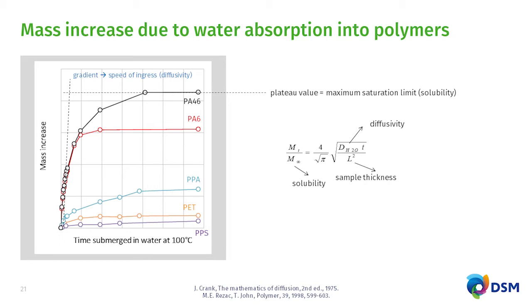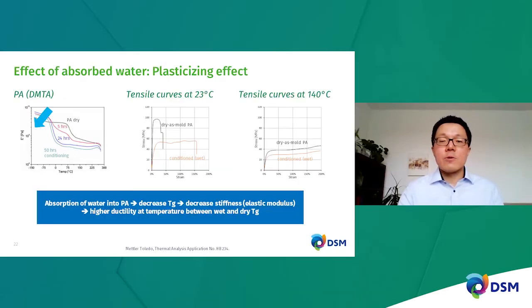The diffusion coefficient you can measure by looking at the gradient of the initial data. The gradient there is related to the speed of diffusion of water inside such a polymer. Usually we calculate this diffusion coefficient by applying a certain model, and the right-hand side figure shows the first order Fickian type of approach that we usually apply to get the diffusivity value from such a curve. But you can also use other types of models for this case. So far we have been discussing the way we measure the speed of diffusion and the amount of absorbed water in the polymer.